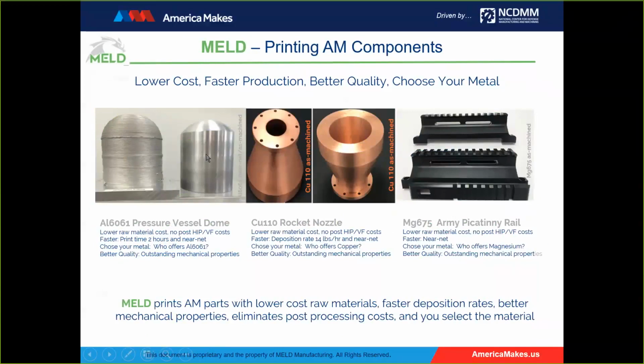And I'm always looking for something sexy about our technology because we're fast deposition. I mentioned aluminum up to 30 pounds an hour. We don't get a lot of complex applications, but in this case, we were able to demonstrate a 54-degree overhang, totally enclosed the top of the dome with no supports.